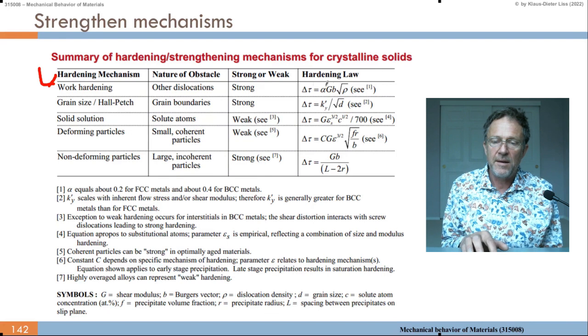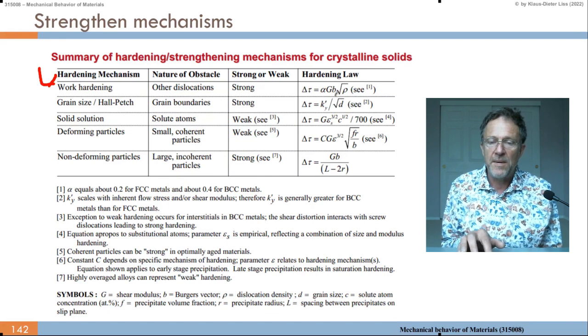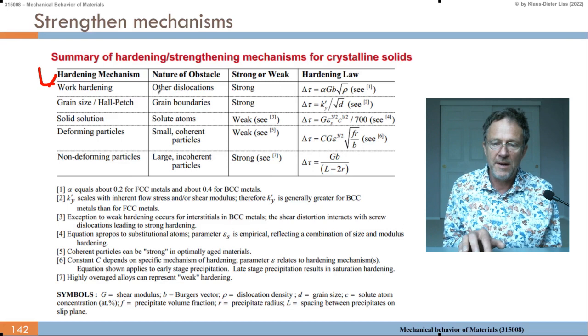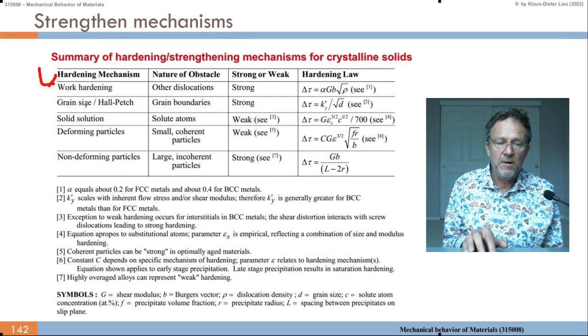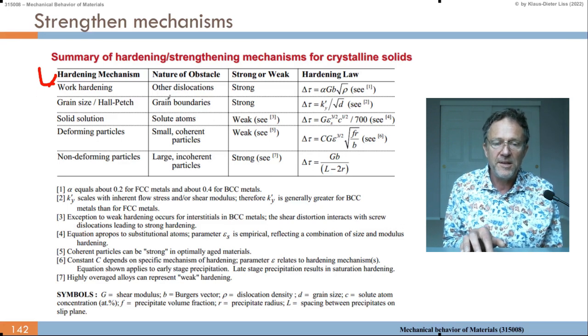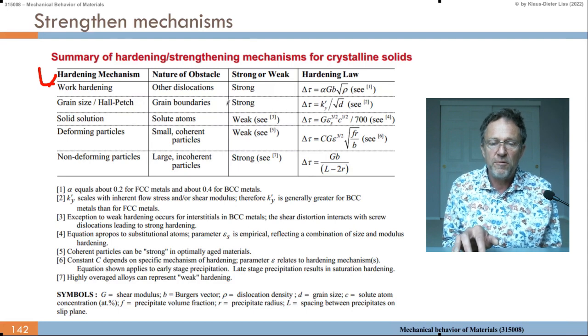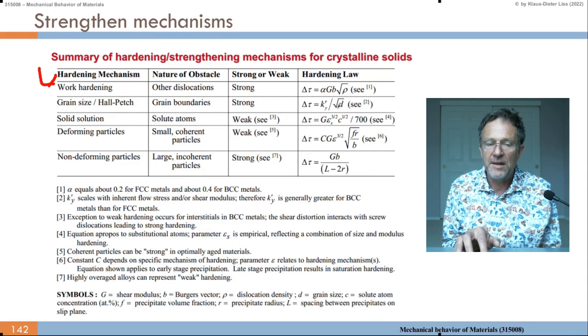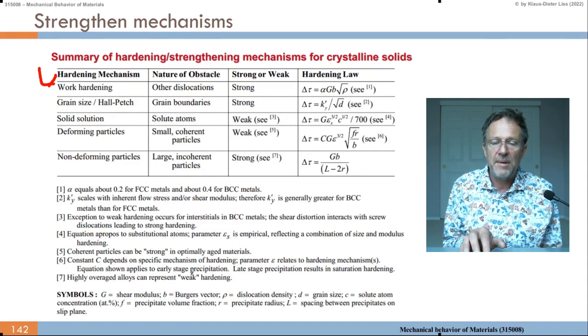And this you can visualize or imagine. The square root of the dislocation density rho is something like 1 over the spacing of the dislocations on the linear scale. Then if you look at the grain size, we call that the Hall-Petch relationship. The grain boundaries play a role, and this is also a strong factor for hardening, and delta tau becomes a factor divided by the square root of the grain size. That means if we make the grain size smaller, there are basically more grain boundaries, then the material becomes harder.